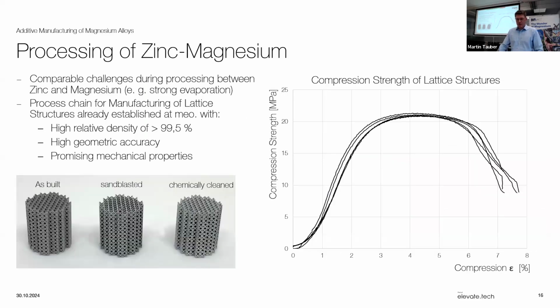Then one outlook for the end of the presentation is we not only do magnesium itself, we're also doing some research on zinc magnesium. So there's magnesium inside, but it's a zinc-based alloy. And also for this alloying class or this material class, we're successfully doing the additive manufacturing, and the density is quite high, and we have a lot of strength because the zinc is an even stronger material than the magnesium.